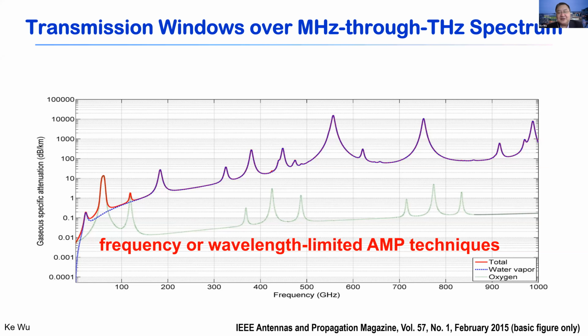It's because at different frequency ranges, you may end up with different transmission loss, which can be caused by different environmental factors such as water vapor, water molecules, and oxygen, and anything you can see in our environment. These two curves show that in very dry weather conditions, compared to wet conditions, you have a very significant difference of transmission over this terahertz frequency range. So that's really the problem for the terahertz system, particularly for long distance transmission.